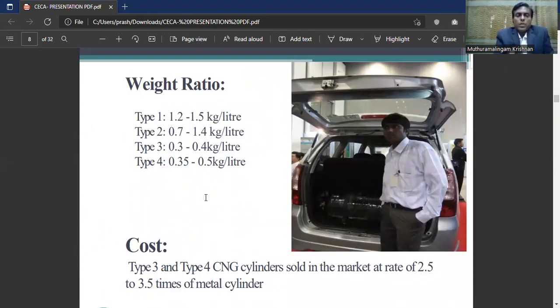Next slide, please. Weight ratio. You can see the Type 1 metal cylinder is 1 to 1.5 kg per liter. It is a standardized one. You can add plus or minus 5 to 10% with improvements in the design, even improved metal, some improvements that took place in the last 7-8 years. These are standard. You can keep in mind 0.3 to 0.4 kg per liter for Type 3, and Type 4 is 0.35 to 0.5 kg per liter.